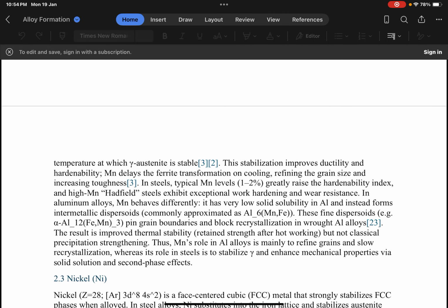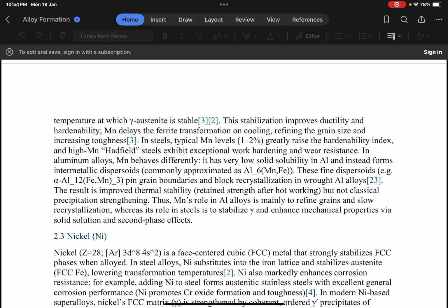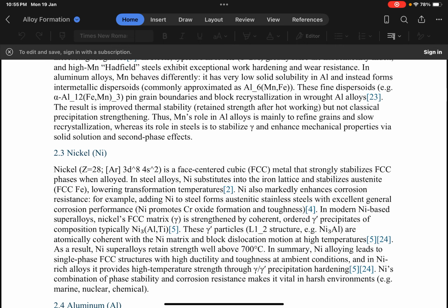In aluminium alloys, manganese behaves differently. It has low solubility and forms intermetallic dispersoids instead of precipitates. These dispersoids pin grain boundaries and prevent recrystallization, improving thermal stability. Next is nickel.